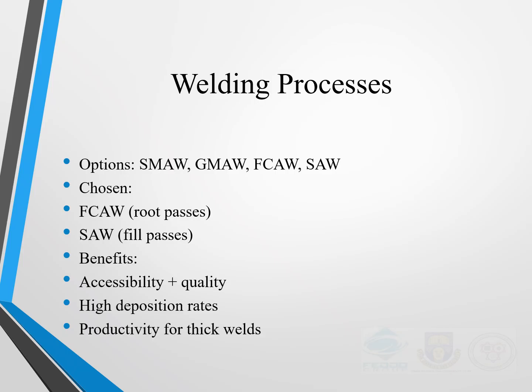For the welding processes, we considered several processes like SMAW, GMAW, FCAW, and SAW. The best option was a hybrid of flux-cored arc welding. That is, FCAW was used for the root passes where access is tight. Submerged arc welding, that is SAW, was used for filling because it gives high deposition rate and productivity. This combination ensured good quality and efficiency.